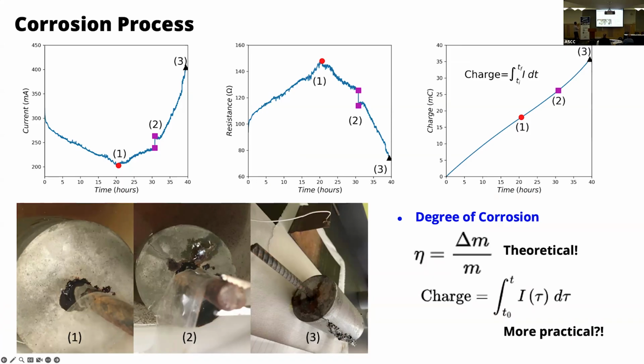So by just seeing this history, the graph of the current, we were able to see what kind of thing is going to happen. So current is going to keep decreasing. At the time, you probably cannot see any crack there. And then the current is going to start going up. Then even micro or small cracks are going to happen. And that crack is going to be propagated and become wider. Eventually, that current is going to go to almost infinity. So that is a simple way to track down the thing.